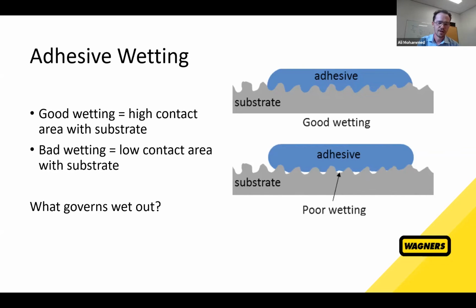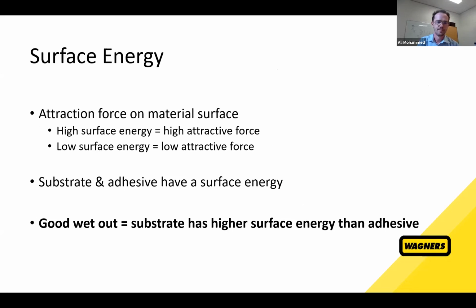So if we're looking for good wet out, and it's a critical component to achieving a good bond, how do we achieve good wet out? Well, let's look at what governs wet out, and that is a term called surface energy. All surfaces have what's called surface energy, and it's essentially the attraction force on the surface of that material.